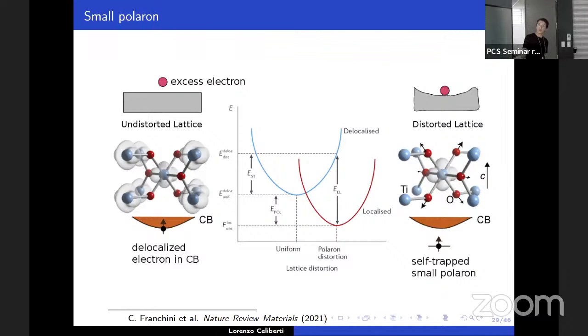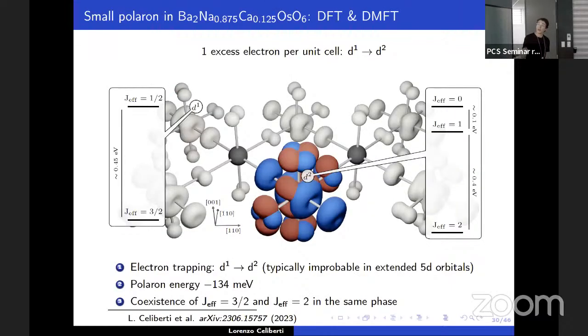So now what happens in our material? Our DFT calculations show that the polaronic solution is more stable. Here you can see these blue and red shapes, which are the charge isosurface distribution, well localized within one osmium oxygen octahedron, whereas the white one is the charge density of the other t2g bands of the osmium sites.